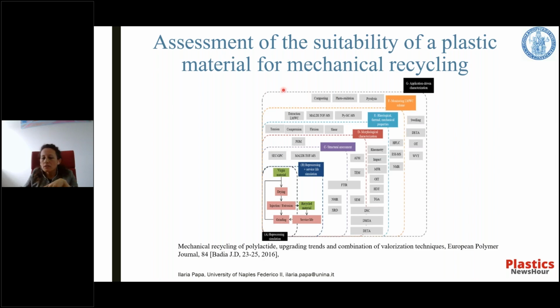For this reason, the effect on PLA of physical treatments, such as thermal annealing, the use of antioxidant stabilizers and chain extenders, the creation of blends or composite materials are being studied. In particular, in the part of the results that I want to show you, the effect of adding a chain extender to the PLA subjected to various mechanical recycling treatments and the mechanical properties can be studied. And usually plastic waste in PLA is treated through mechanical recycling, but when its properties become such as to compromise its possible future application, other ways are preferred, such as composting, incineration, or chemical recycling plants.